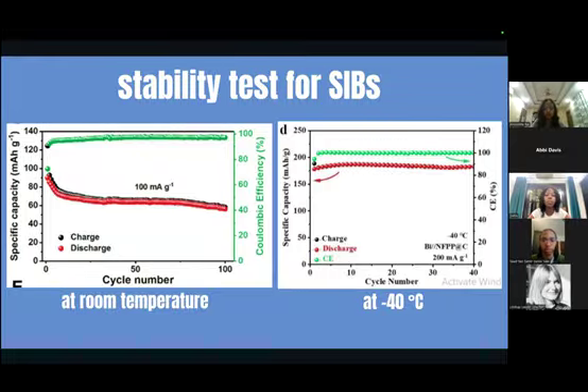So over here, black dots are representing charge capacity, red dots are showing discharge capacity, and green dots are showing the Coulombic efficiency. In the first graph, at 100 milliampere per gram and at room temperature, the sodium ion cell maintains high Coulombic efficiency, but shows a steady decline in capacity from 85 to 40 milliampere hour per gram over the course of 100 cycles, which is indicating efficiency is high, but long-term capacity retention needs to be improved.